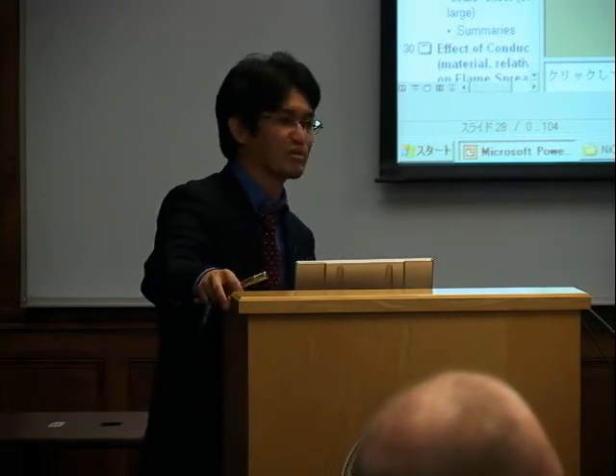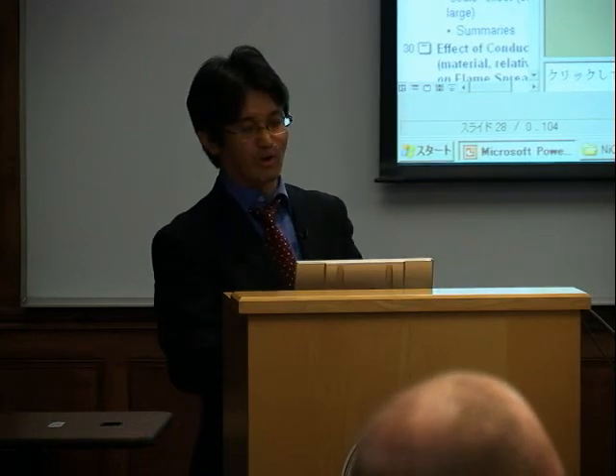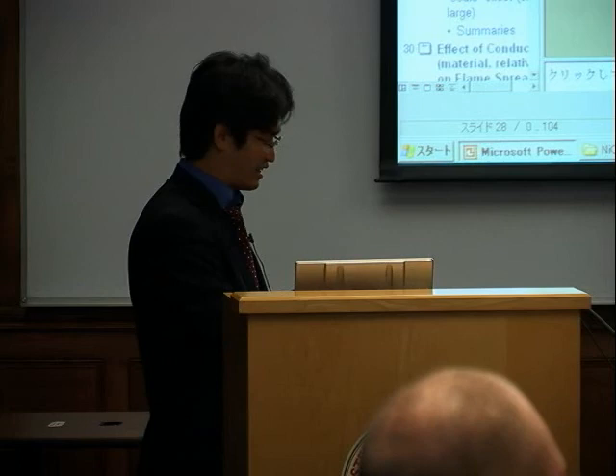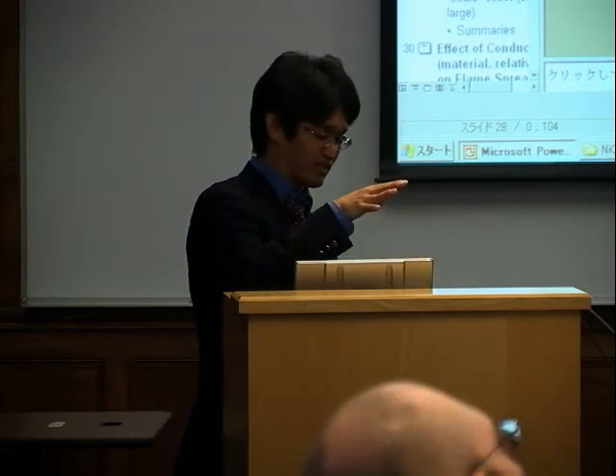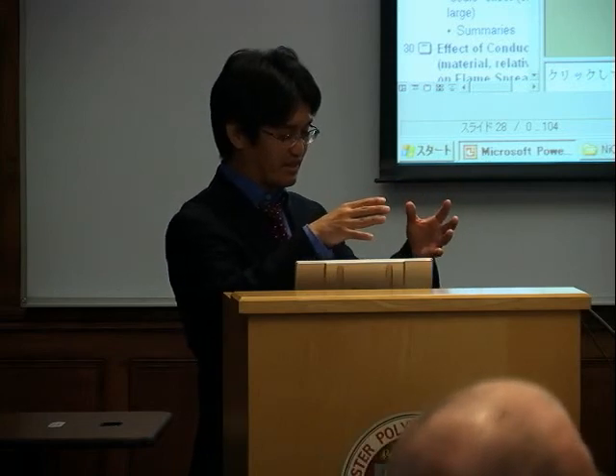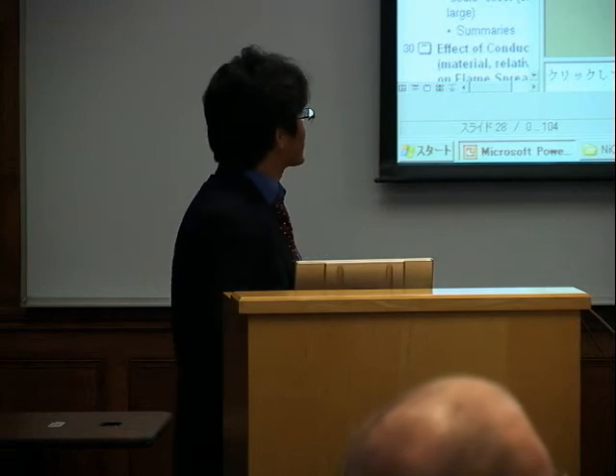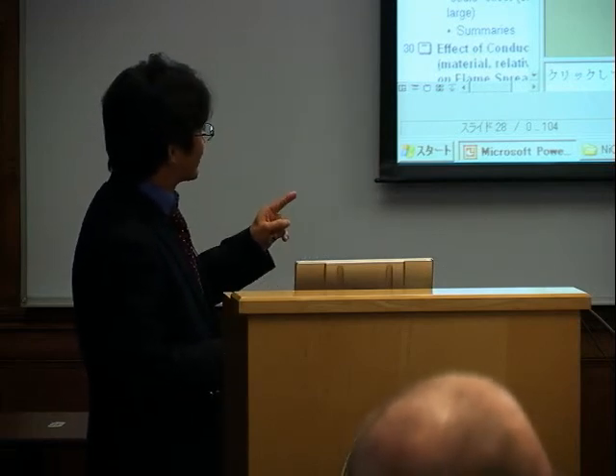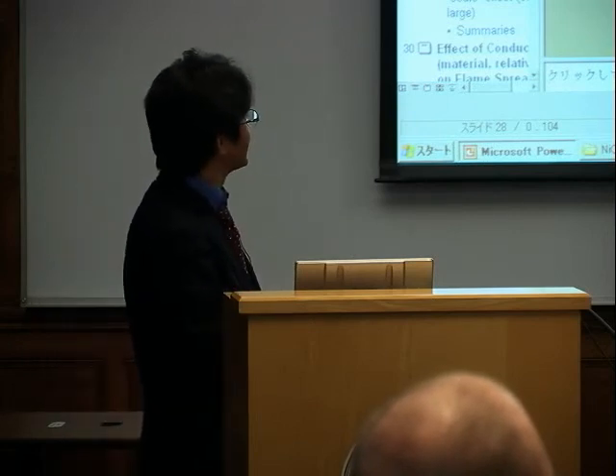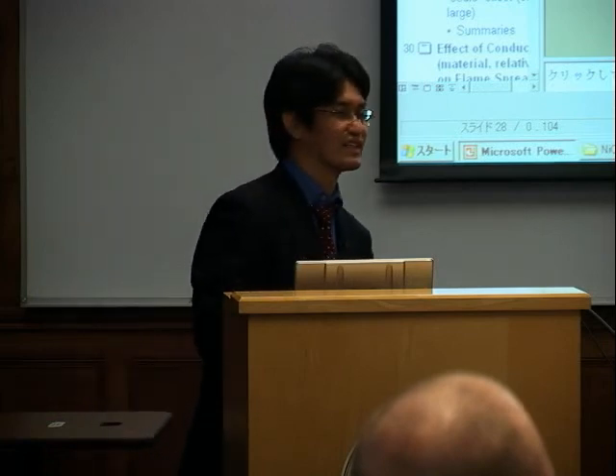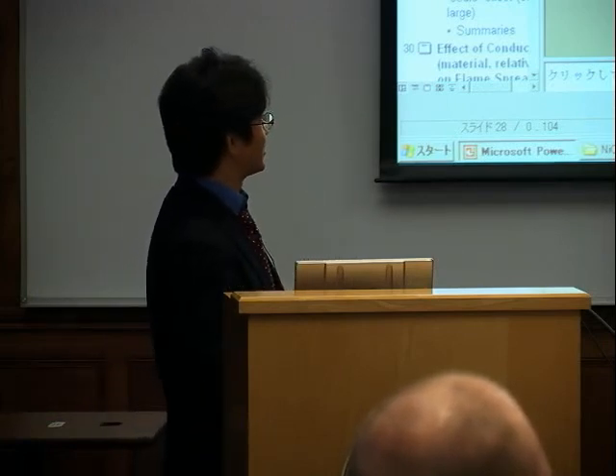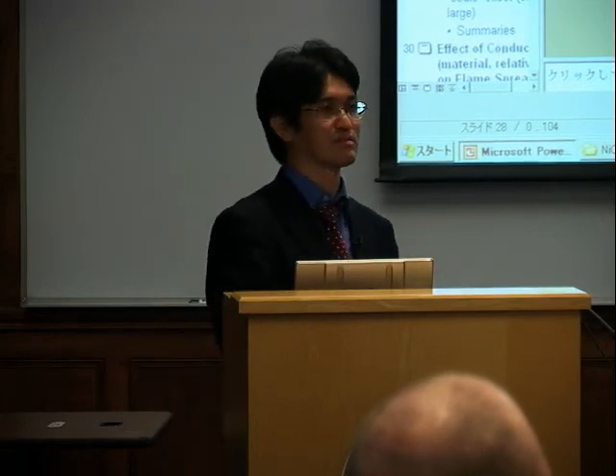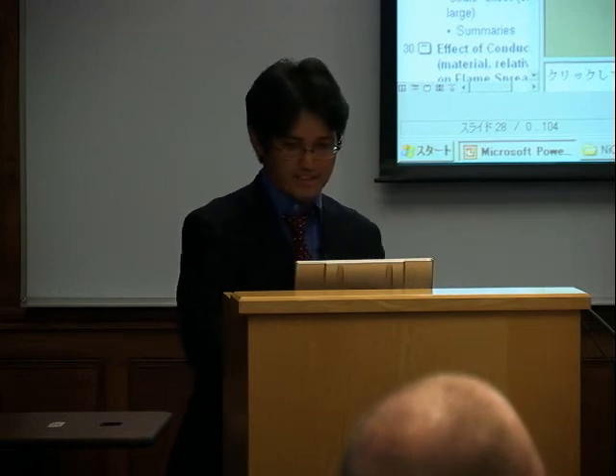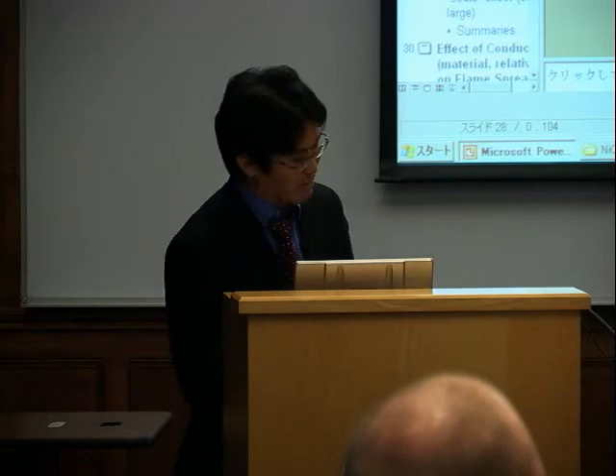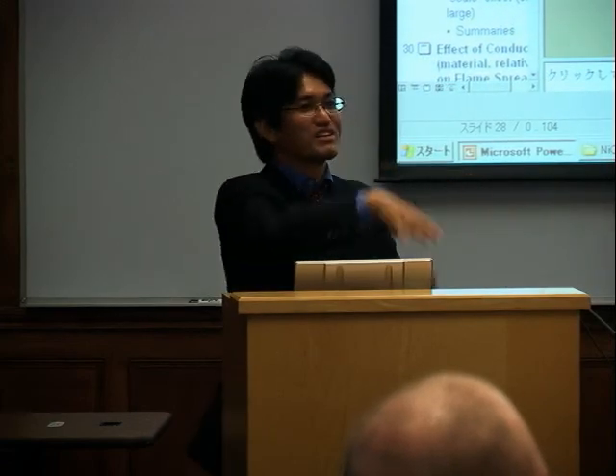So this is why the shape always tends to get a higher heat flux, a higher heat conduction rate, or a higher amount of heat. Of course, as you mentioned, compared with the radiation heat flux over here, this one is much more. But the amount of radiation heat flux has to be quite small as compared to the conductive heat flux. But I understand you saying that at 100 kilopascal you had more buoyancy flow, so your flame shape is like this and not like a spherical shape.